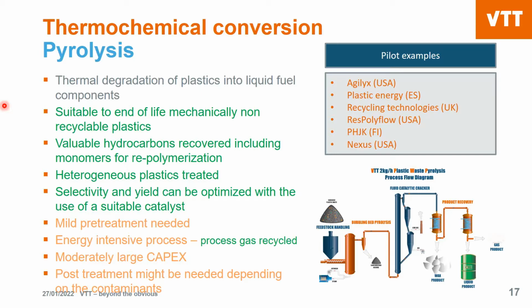It's a bit energy intensive process, but one solution to that is process gas, which means that when you have condensed all the liquid product, the gases which are coming out of the process are still rich in hydrocarbons, so they can be used as energy for the process itself, which makes the process self-sustainable, or you can say that the gas is providing the energy for the process. The capex of this system can be moderately large, which means that you need higher investment to make this type of system, and post-treatment might be needed depending on the contaminants in the pyrolysis oil.